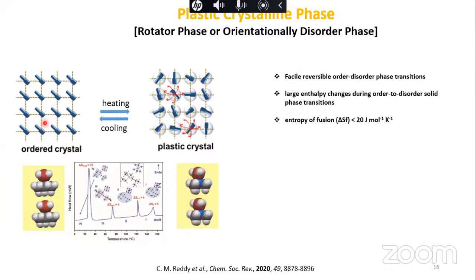So it normally happens from single crystal to single crystal because you're not generating a lot of strain in the crystal, simply because the molecules have to rotate in their own position. That is why these phase transformations are very, very easy in these crystals. And then you also have a large entropy of transition but a very small entropy of fusion.